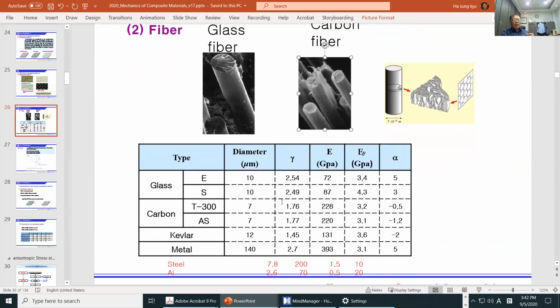So these are little different values, but the values are not unique, depending on the manufacturer and so on. But as you can see, overall the carbon fiber density, gamma is the density. Okay, so diameter is 7, and the density is about 1.7 versus 2.5. That's the one you need to remember. And the carbon is about 220 gigapascal, and this is about 70, and as you can see, transverse wise is very weak.